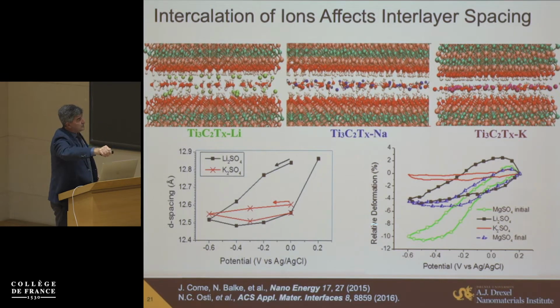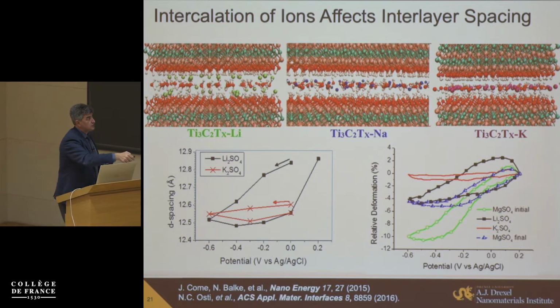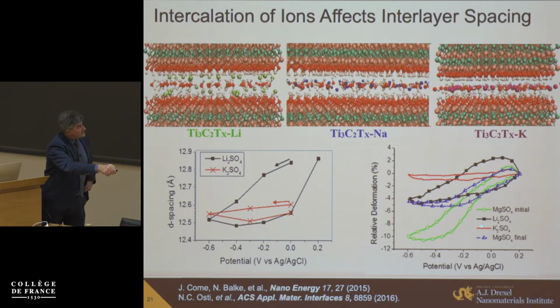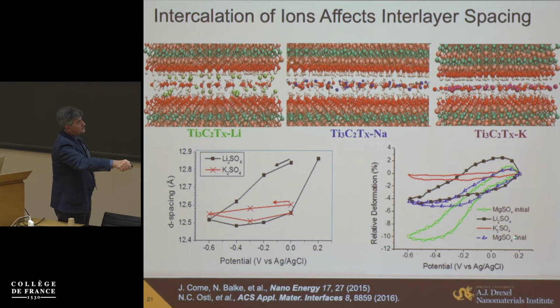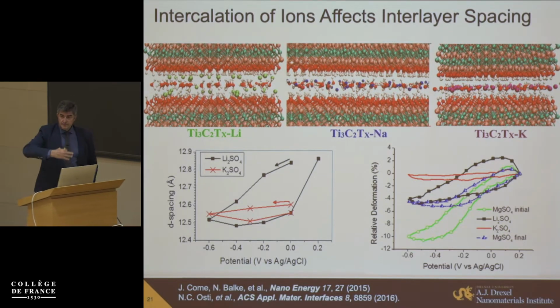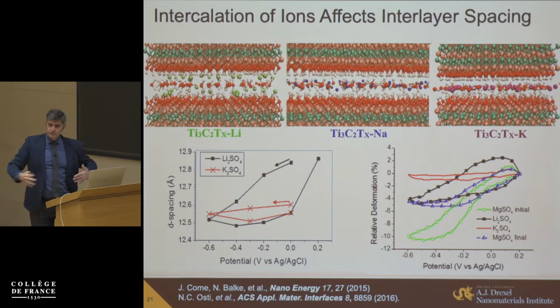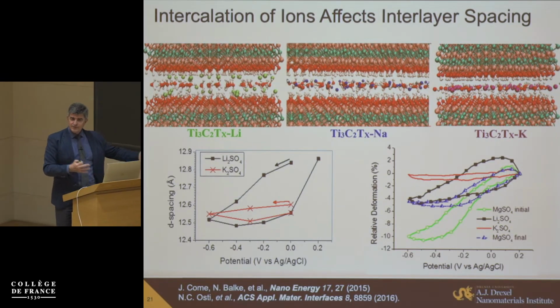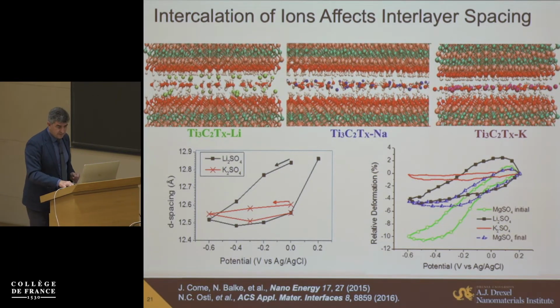layer more and more ions, what you will see, sometimes you get contraction because you have negatively charged surfaces and positively charged cations going in between, so there is electrostatic contraction of electrodes here. And there can be almost no change, like in case of potassium, for example, from potassium sulfate here. And there can be, depending on potential, contraction and then some expansion. So again, it depends. You want to have large expansion if you build an electrochemical actuator. You want to have minimal expansion if you, say, build a battery.